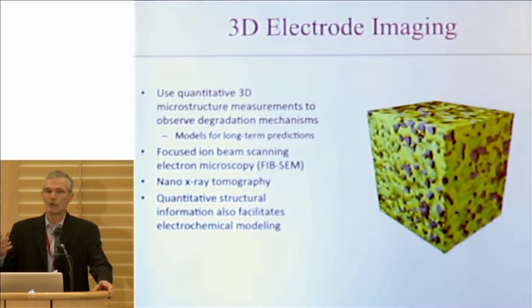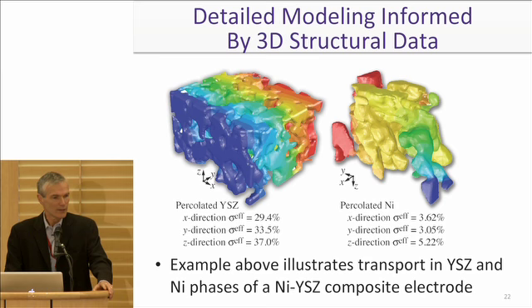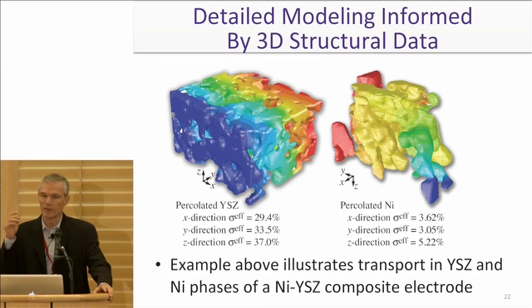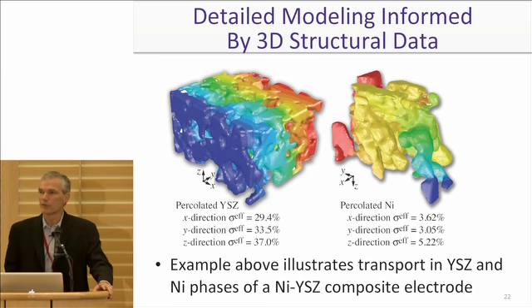What we want to do is go in before and after cycling these devices, after degradation has occurred, look at the microstructure and try to understand what are the mechanisms of degradation so we can hopefully avoid them. Another thing we can do is take this structure and port it into an electrochemical model. This is a result from Bob's group where we've done that. We've taken a three-dimensional structure, put it in, and he started calculating the transport of electrons or ions or gas phase through the different phases that are present in the electrodes.